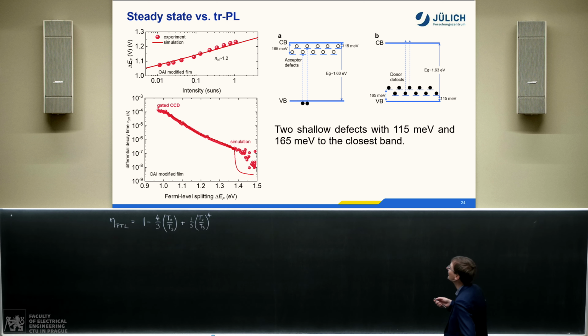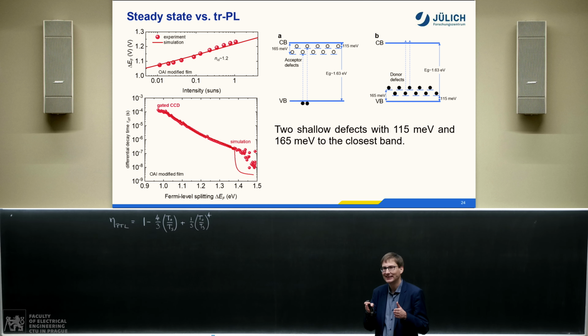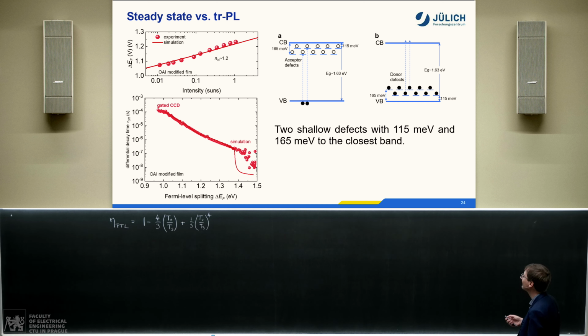If you wanted to get this nearly constant slope for like 400 milli-electron volts in Fermi level splitting, we needed 2 of them. Because each trap has a transition from 1 to 2, and you can't really have one trap and keep the slope forever. So for 2 traps it worked, and maybe we need a distribution of traps, which is where the tails come in, of course. And you can also see for this bit, we'd need probably a 3rd trap. But we were too lazy to do this.